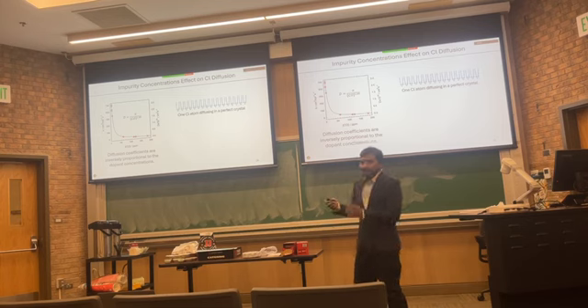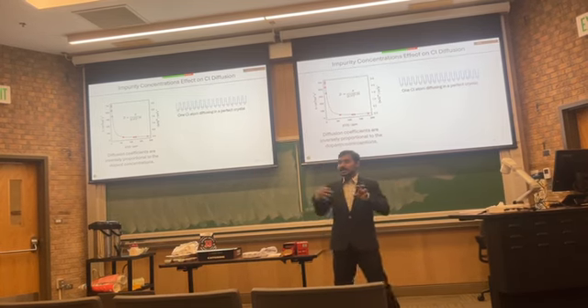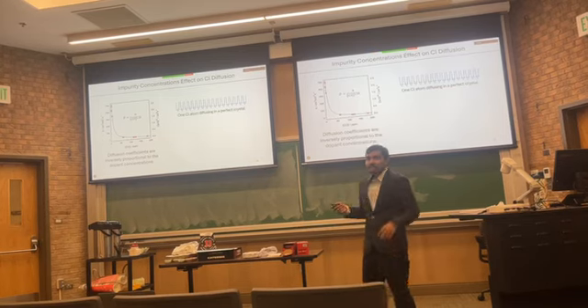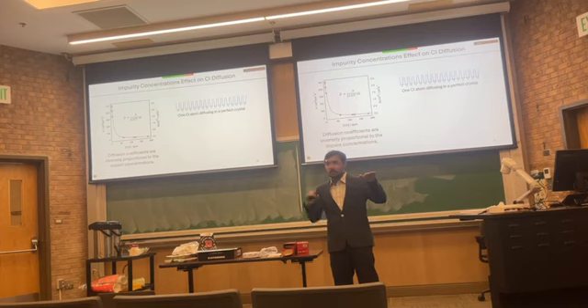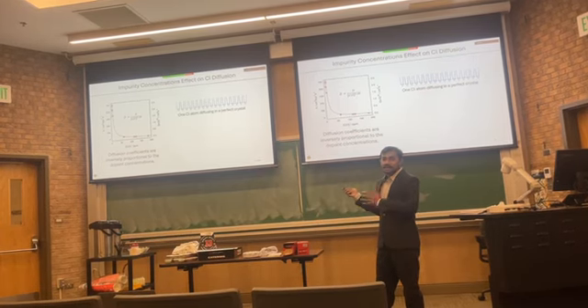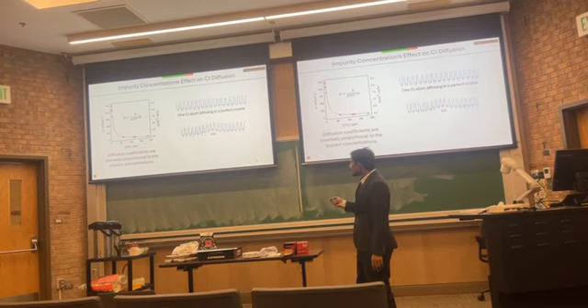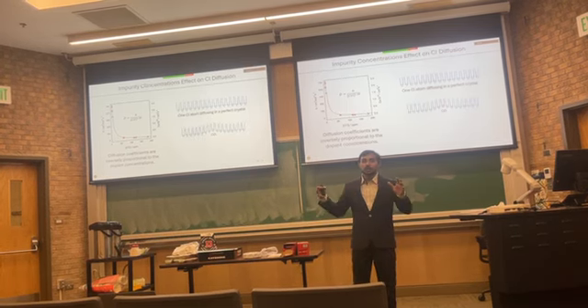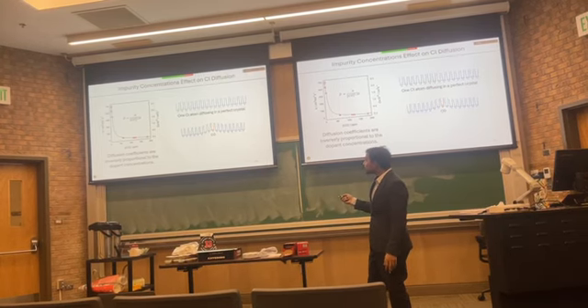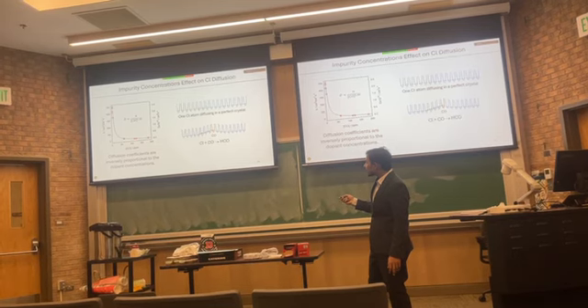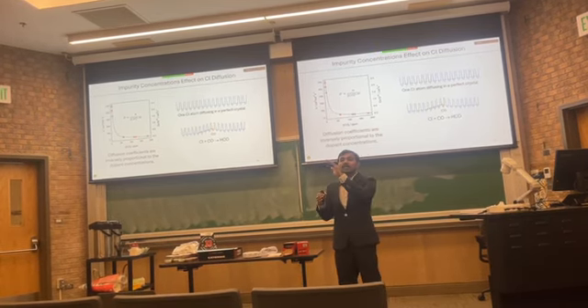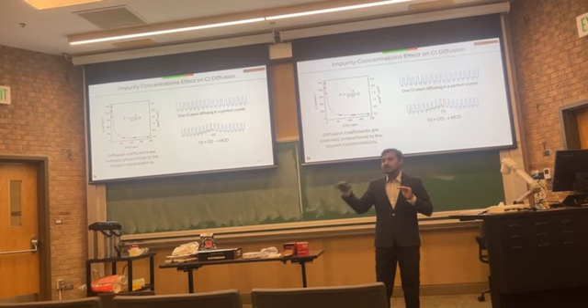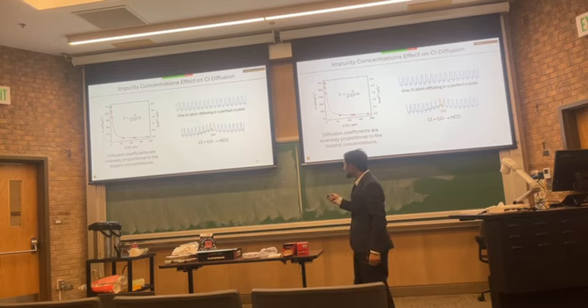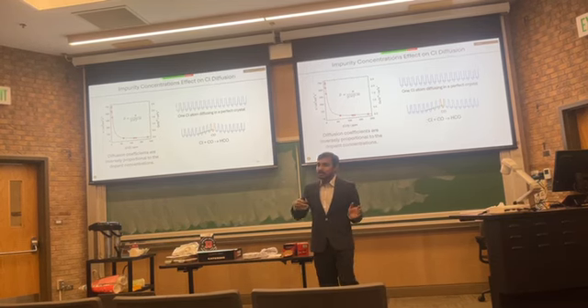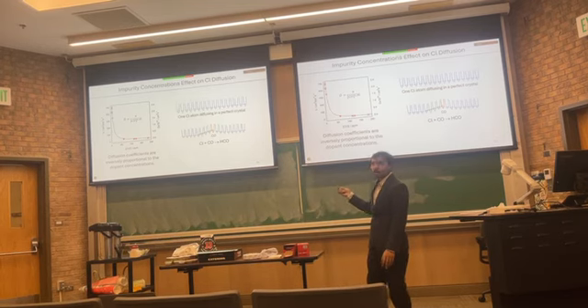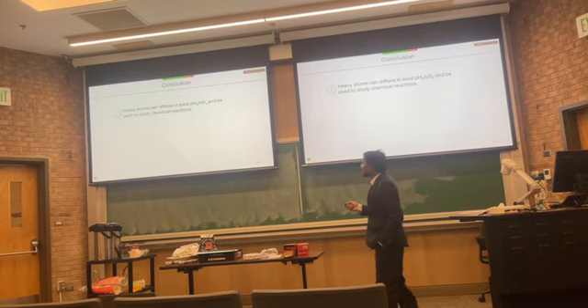So when you have quantum tunneling, let's say you have a nice single crystal, one chlorine atom. If it diffuses through the crystal, it will go from one lattice site to another without changing the energy state from lattice 1 to lattice 2. We call it resonant tunneling. So resonant tunneling is faster, but if you have some impurity, that will perturb your crystal field. So if you have a chlorine here, that chlorine wants to go this way, but now it needs to go up here. So it doesn't have that energy resonance anymore, so it's non-resonant, and that's why it slows down. So if you increase the impurity concentration in the matrix, it slows down because you have all these non-resonant diffusion processes.